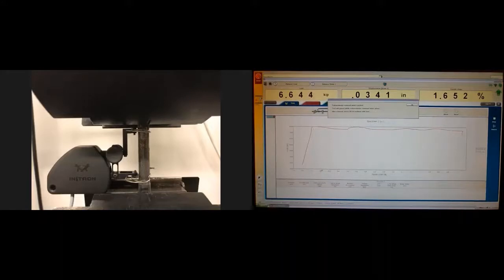So we would use this point and project it to this curvilinear portion of the tensile curve, parallel to this initial portion. So it's going from here down to here. Somewhere around here, we would see the yield strength, the engineering yield strength. Now, with this flat behavior of the material, it indicates that yielding has some plateau, showing that slip systems, some of them, got activated, and dislocations started moving, and they probably caused some geometrical change because of plastic deformation. And this geometrical change is irreversible. So when we unload the sample, it will change the shape.